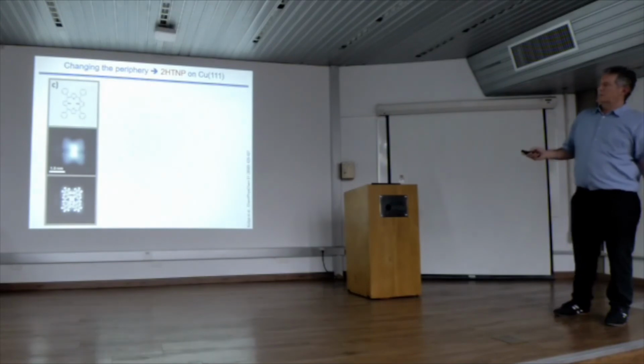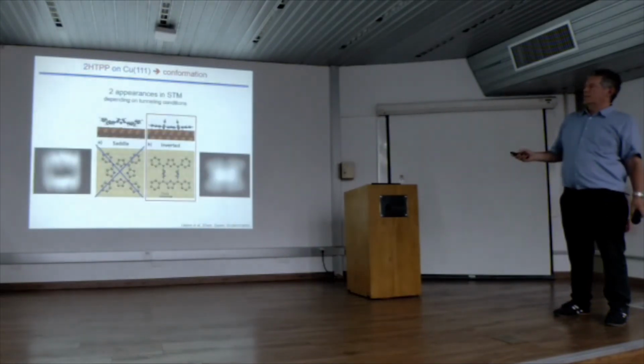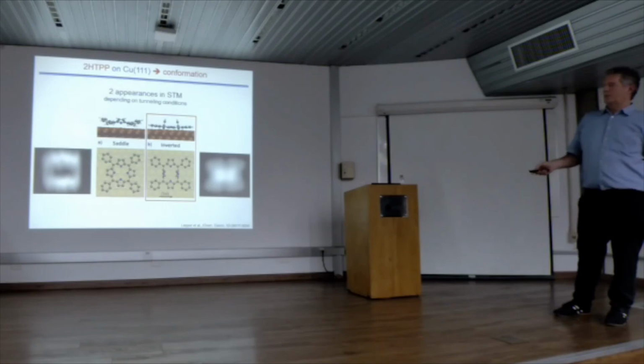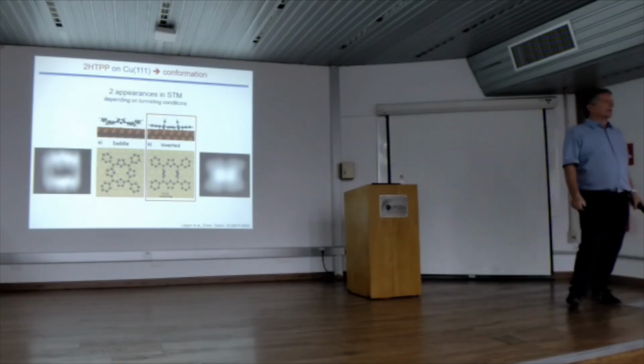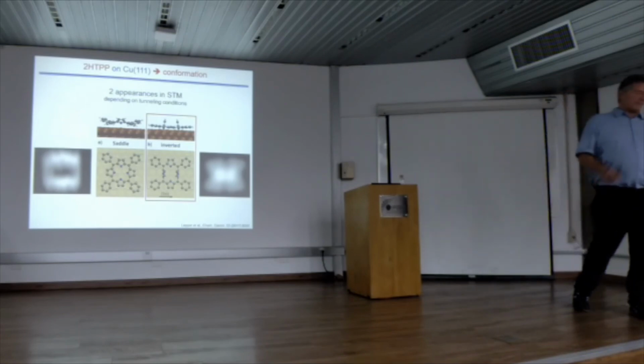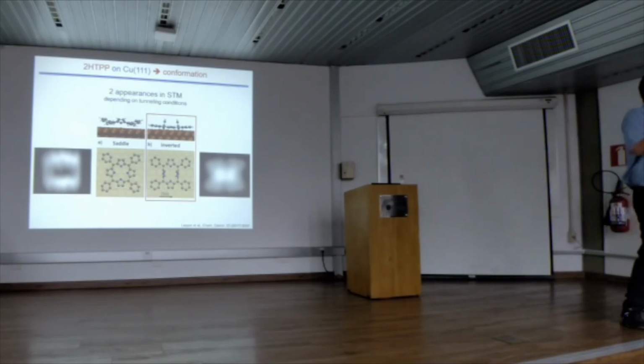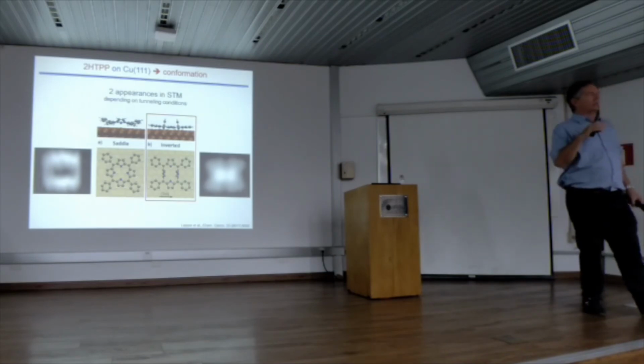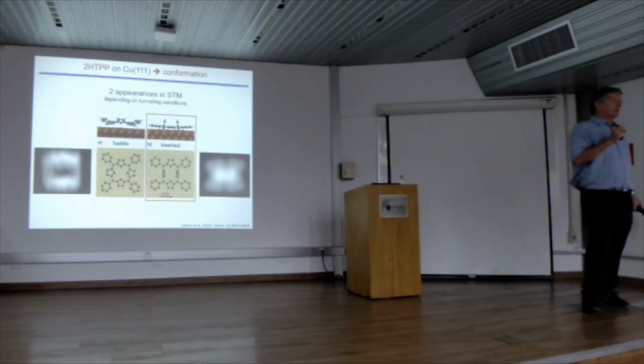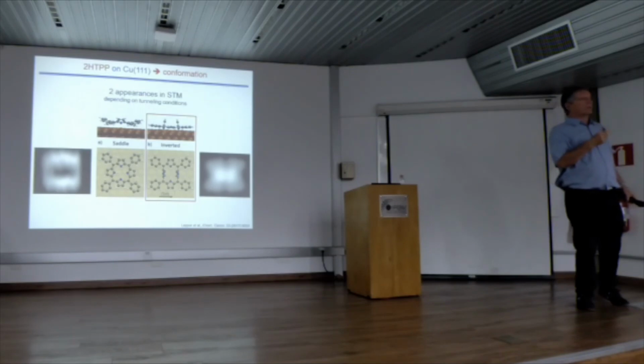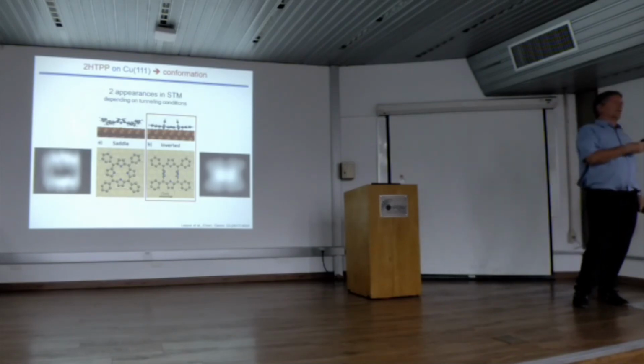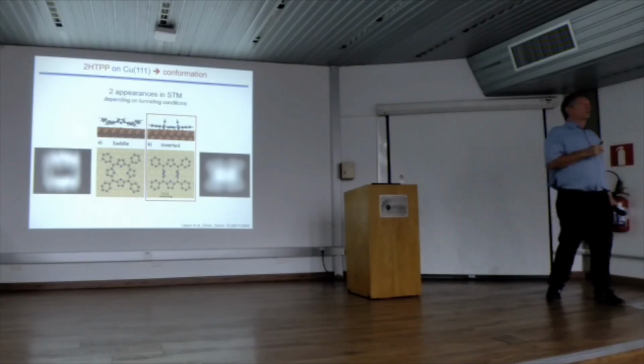And yeah, tip is very important. So in all effects, in particular diffusion, or we also studied switching of porphyrins on surfaces, you have to be very careful with the tip. So what we did is we changed the voltage. We tried to get the current low. We changed the speed of the images just to see where there is an influence of the tip and where there is not an influence. The mode that we typically use is the topographic mode.